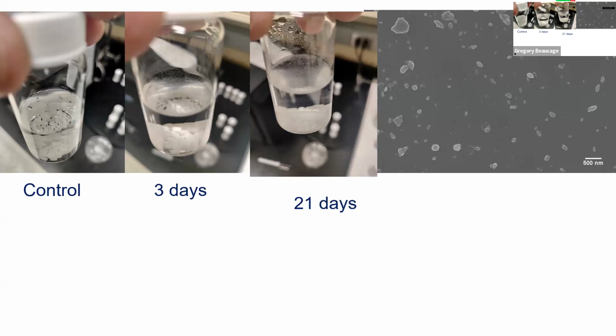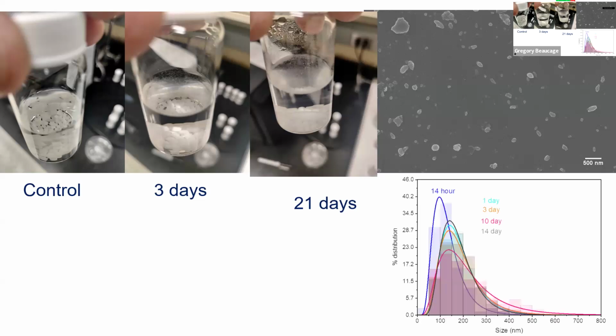And I'm going to show you more pictures, but that picture should scare the living daylights out of you. Now, we did a size distribution as a function of time. This is the same PET, different days. This is the size distribution. You always end up at around 100 nanometer size with a very long tail. That size does not change as a function of how long I stir. So it's telling you I'm making particles of a certain size. They break down until they get to that size, but they don't go below that size. So you're making 100 nanometer particles over and over when you stir this. And that's going in your body, and that can get endocytosed by cells. That's the first thing you should be thinking about. You should be deeply worried.